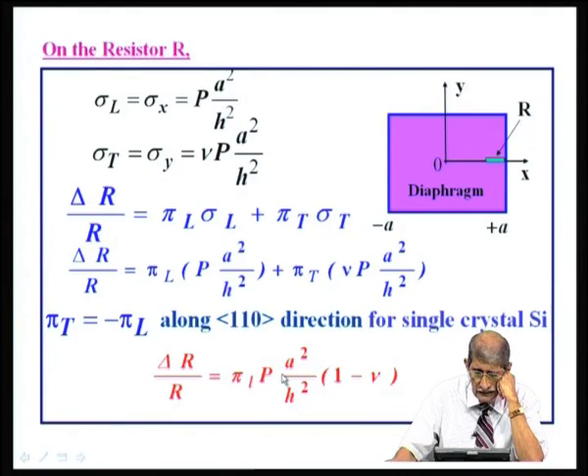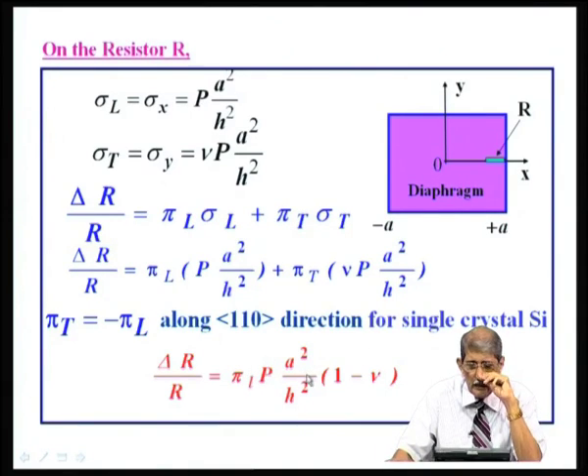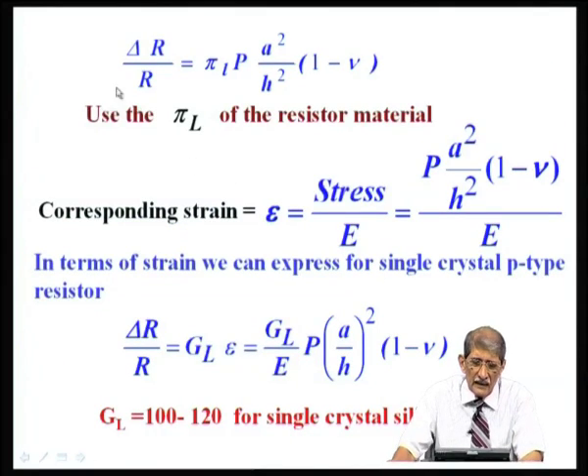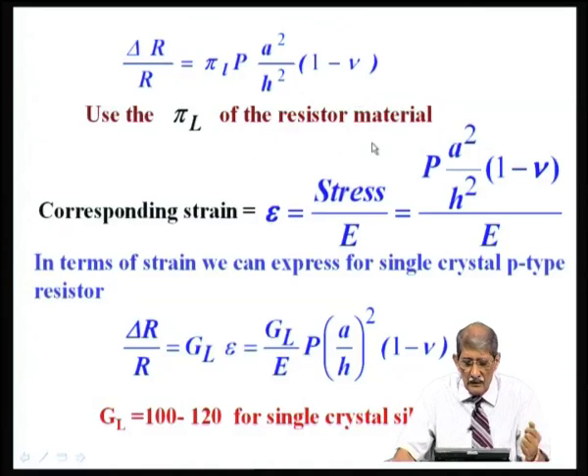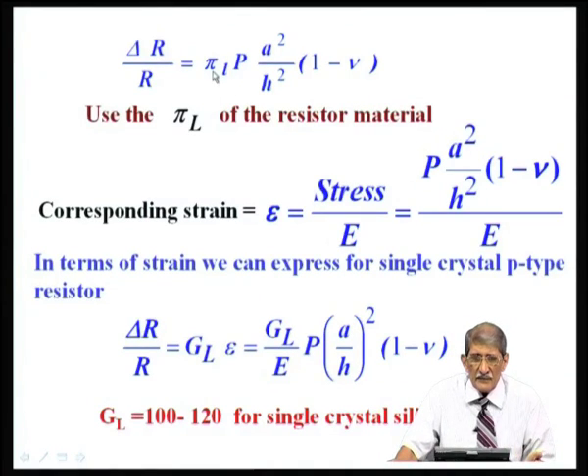So, you can now tell very comfortably that if you know delta R by R and pi L, and the other dimensions are known, you can tell what the pressure is. That is how the pressure sensor works. So, delta R by R is pi L into pressure into A by H whole squared, where A is half of the width of the membrane, into 1 minus nu. Nu is Poisson's ratio, about 0.3. So, you can express this in terms of the piezoresistive coefficient. You can express it in terms of the gauge factor also, because pi L and G L are related through the Young's modulus.